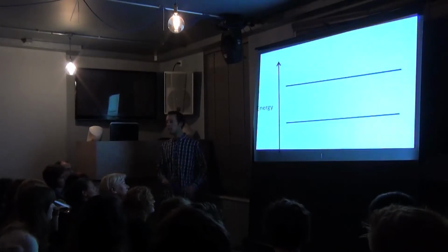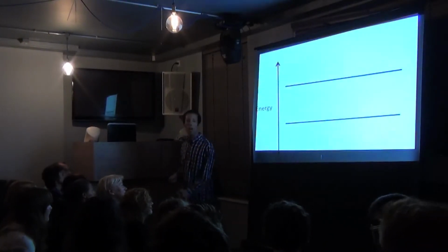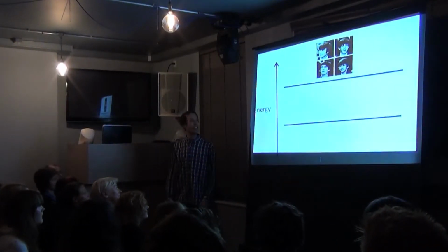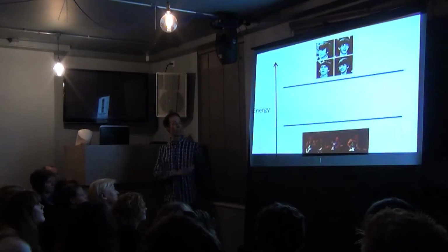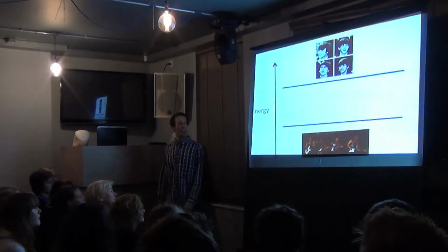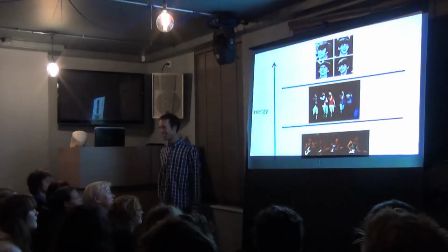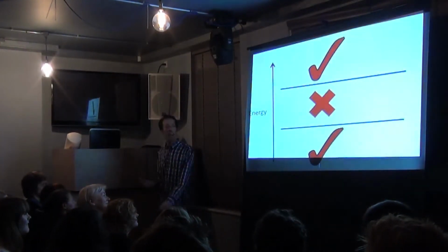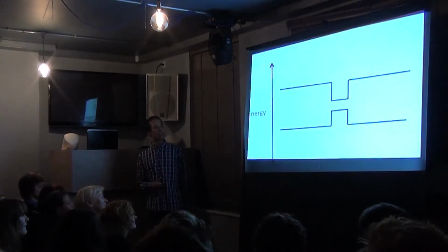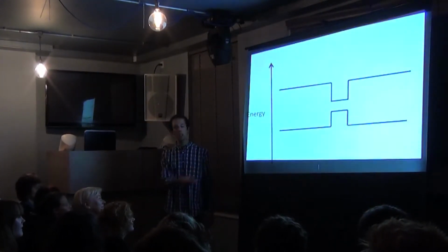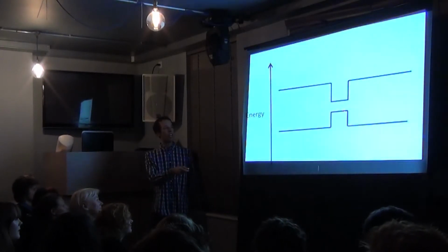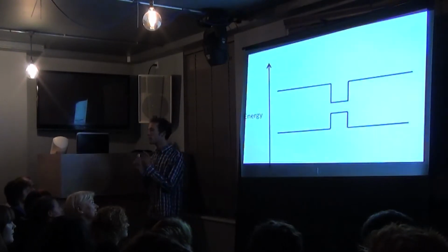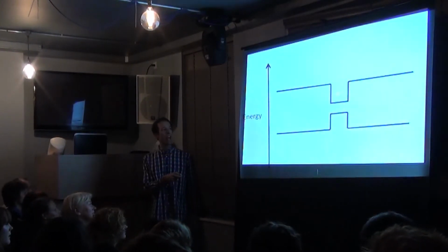As you go up the screen, the higher it is, the higher energy the electrons have. At the top, there's a band full of energies that they can have. At the bottom, there's a band full of energies that they can have, and the gap in the middle is not a band. That's a place where you cannot have any electrons of that energy. And what I do is I actually put another material, another semiconductor called indium arsenide in the middle to create this little kind of kink in the band. So now we've got some places inside this tiny, tiny blob of indium arsenide where we can have electrons.